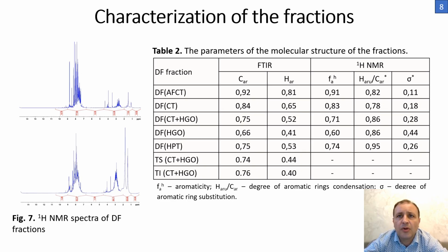Distillate fraction from coal extracts in coal tar and anthracene fraction of coal tar exhibit higher carbon and hydrogen aromaticity and a lower degree of aromatic ring substitution. Other fractions are characterized by relatively low aromaticity, as can be seen from the Car, Har, and σ* indices, and by a higher degree of aromatic ring substitution.